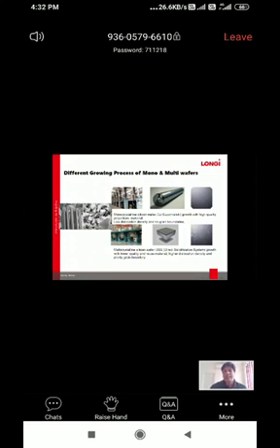Now this monocrystalline wafer has all the benefits that I stated earlier: it has low dislocation density and no grain boundaries, so lesser charge trapping centers, and as a result, better efficiency.